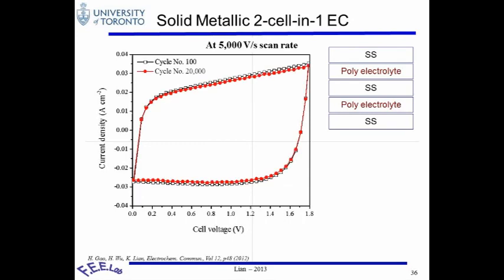So it retains the high rate performance even when you stack them together. We also looked at the cyclability, and we only went to 20,000 cycles. This can go really fast, but the point here is that at 100 versus 20,000 cycles, they are pretty much overlapped. So the cycle life is very good as well.